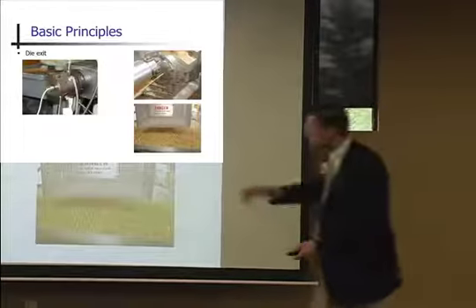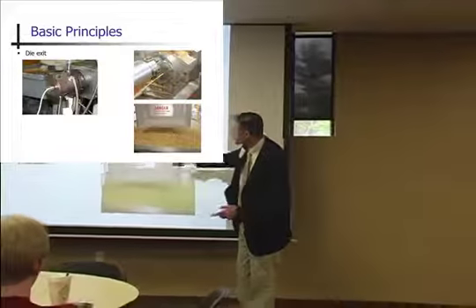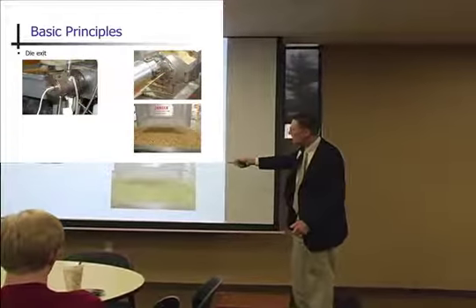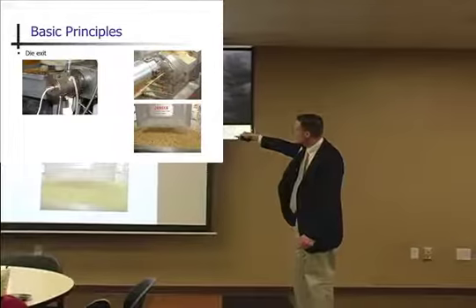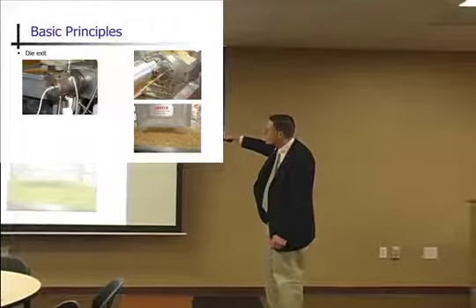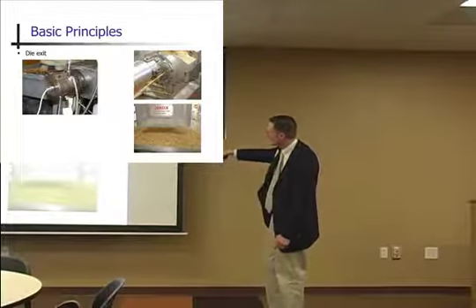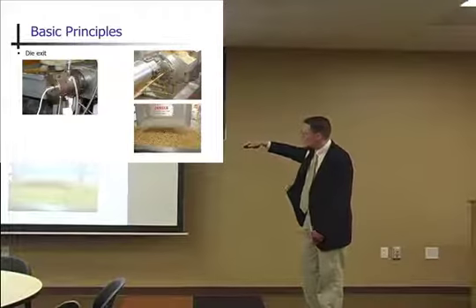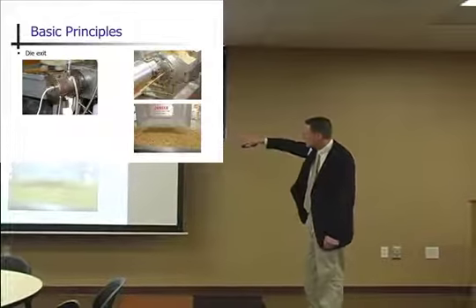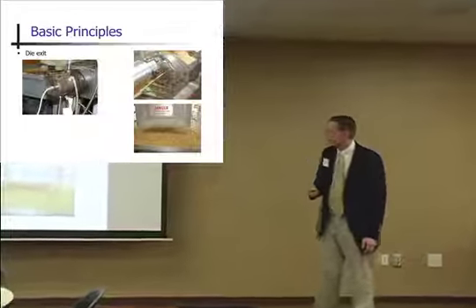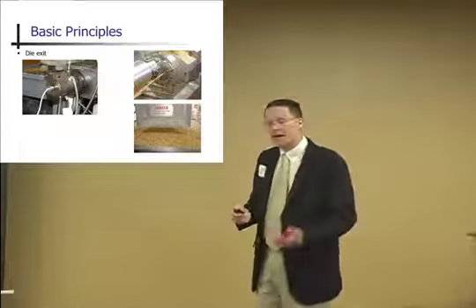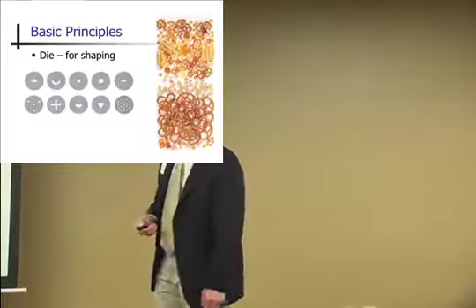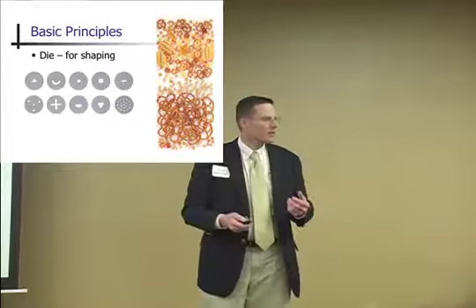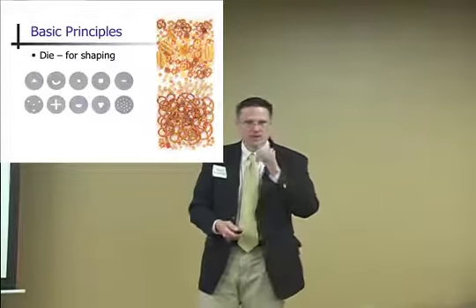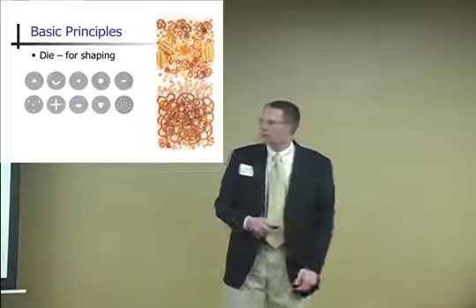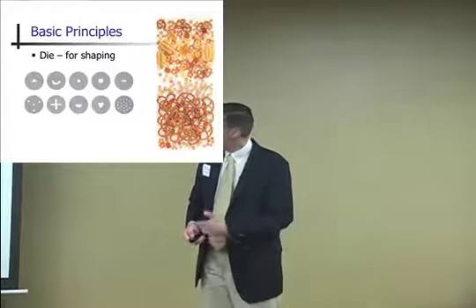So if you take a look, this is a single screw laboratory scale extruder, not a lot of pressure, not a lot of expansion. This is the discharge of a Wenger, a little higher flow rate. There's a little bit of expansion, but not much. Now this is when we turn the cutter head on, put the guard in place so we don't cut our students' fingers off, then we get better expansion, get the products that we typically think about in terms of pellets. So the die opening is key, it's critical. You can make all sorts of shapes. Typically what we think about is little round pellets, whatever millimeter size that we want to buy from Silver Cup or Rangen or whoever we're going to buy the pellets from. But you can make all sorts of things.